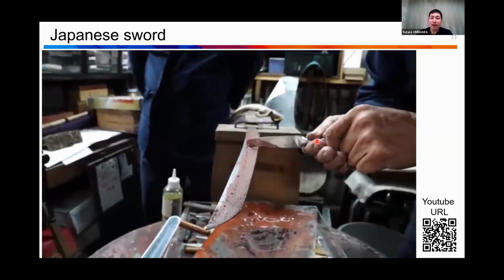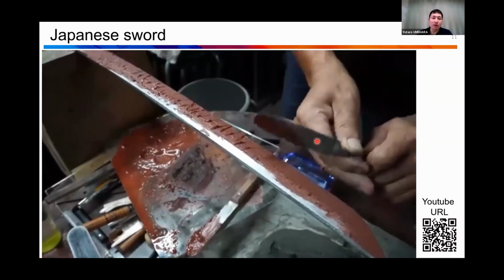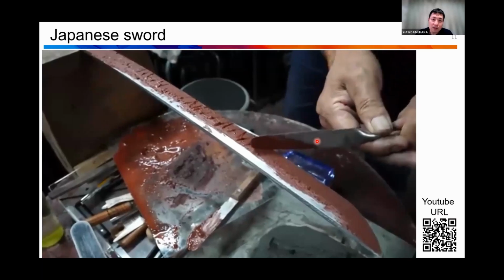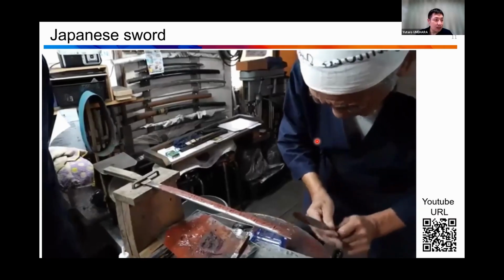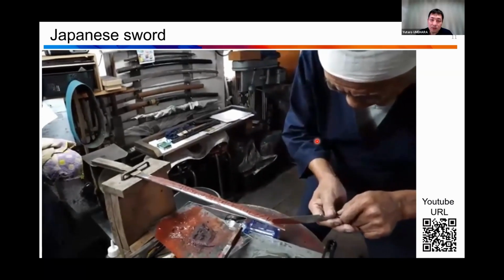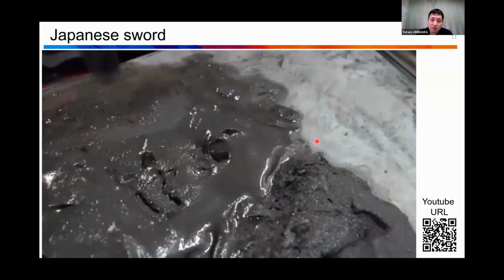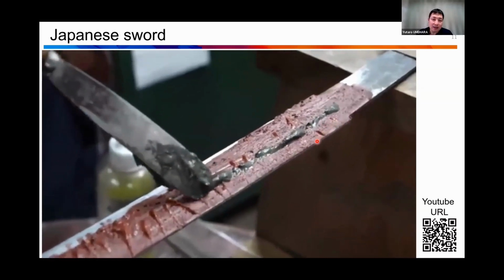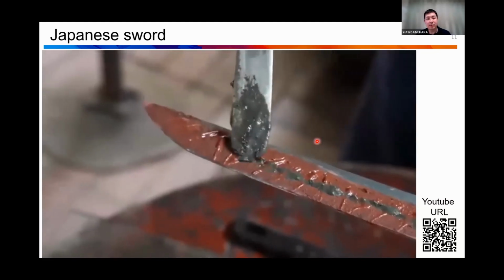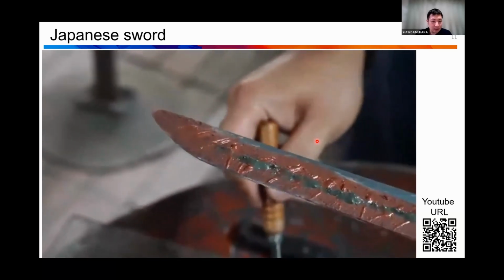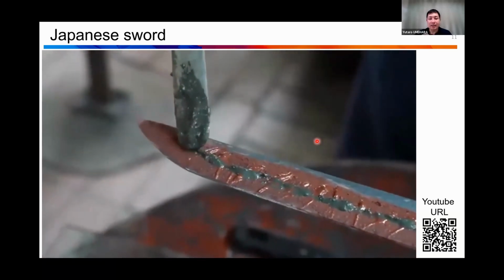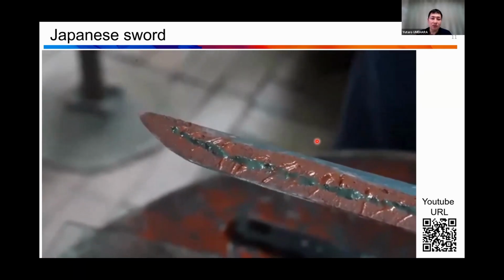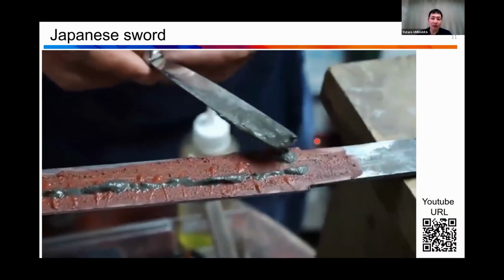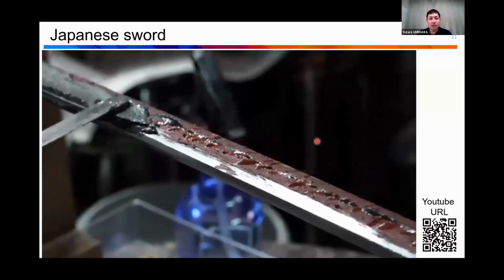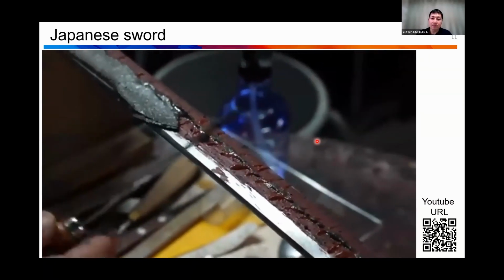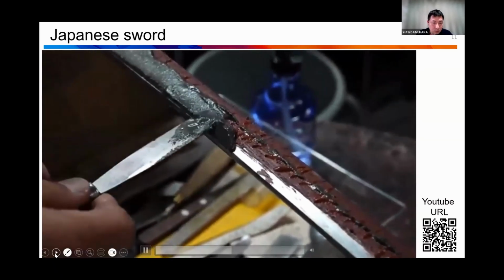And also they choose a different material on the surface. This red one is the same one, but they made some pattern. After that, they choose a different clay on a different side, because the spine side maybe needs toughness, but the blade side needs hardness. So they choose a different thermal conductivity clay to add on the sword. And then also they change the thickness.